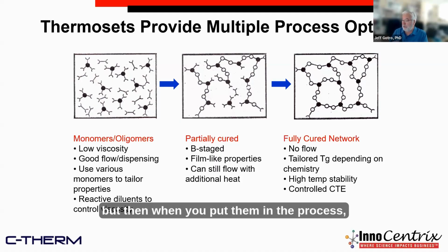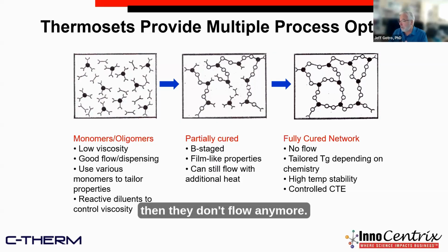But then when you put them in the process, like in a lamination press or as an adhesive, you glue the chip down after you put the semiconductor chip, and they can still flow and cure with additional heat. Then once we have this fully cured network, 99+% of the molecules have reacted, and they don't flow anymore.